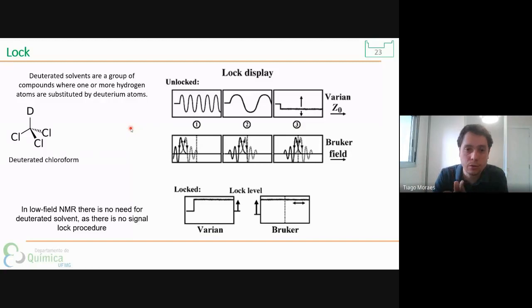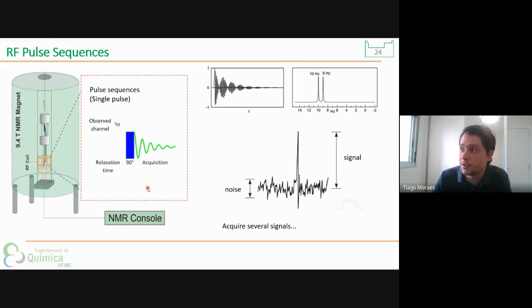And also, in high resolution NMR, we use deuterated solvents to keep the frequency correctly, to maintain a good spectra in the high field, high resolution NMR. But in low field NMR, we do not use these deuterated solvents, right? So this is better for low field. There is no need for it.